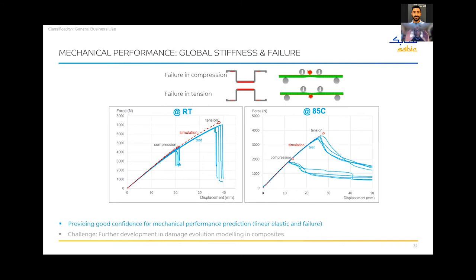I'm going to show you one flavor of the results and compare the CAE simulation versus the actual experiment. Let me focus on the left-hand side. Let me get my pointer back up. Here's the data at room temperature, force versus displacement. When I did the test in tension, you can see the actual experimental data in blue, with replication showing some nice tight data, both in terms of stiffness as well as strength. It's pretty good for this complex part.